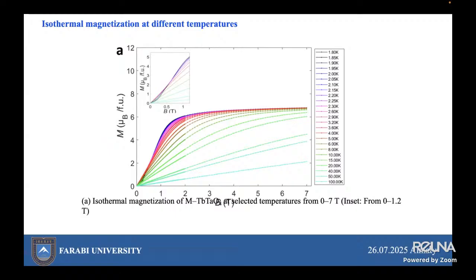to 1 Tesla, with the initial slope of the curves noticeably larger at low temperature, again indicating strong magnetic interactions and the presence of magnetic ordering. This overall trend suggests a field induced transition from the paramagnetic to an ordered magnetic state, or the presence of spontaneous ordering at low temperature, which weakens and vanishes with thermal fluctuations.